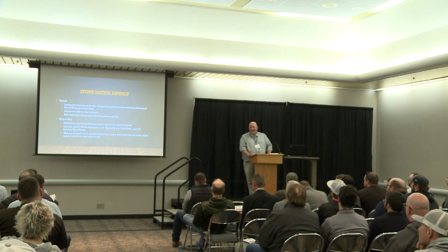Typically the HMA projects require a chip seal every 3 to 5 years. The North Dakota DOT, on the existing SMAs in the Fargo district, has only done some crack sealing. And the future is to look at possibly a fog seal of the entire coat sometime in the future, but when we looked at them last summer, there was no need to do anything yet. Long-term preventative maintenance or rehab would be to do a micro mill with an ultra thin bonded wear course possibly, or even a reconstruct mill and SMA overlay for that. When it comes roughly 20 to 25 years old is what we're hoping for.